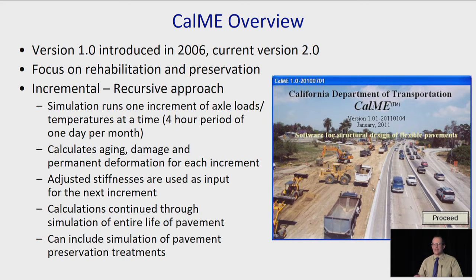The main idea for this came from Per Ullidtz at the Technical University of Denmark, and he was a major driver for much of the technology that we used at the beginning. So basically, in incremental recursive, you start with the initial properties of the material in terms of aging, damage, and fatigue damage, and permanent deformation. In the first day, hours of the first month, you apply loads and you damage the material. You adjust and you age it. You adjust the stiffness of the asphalt based on the aging model and on the incremental damage that occurred.